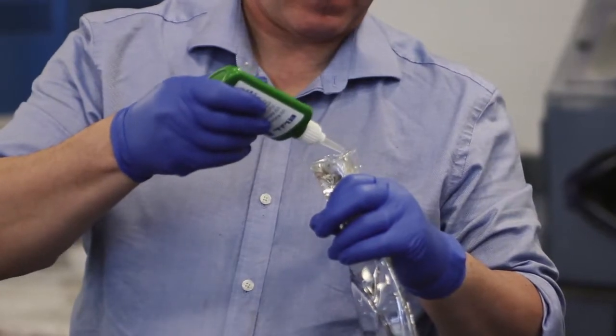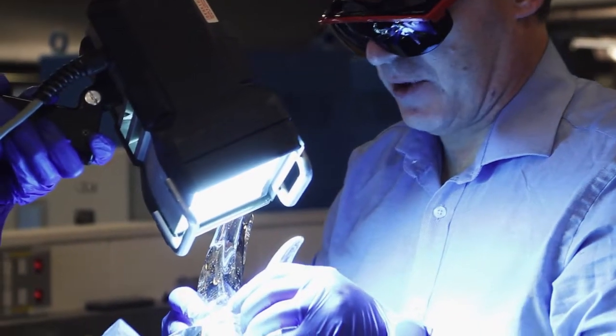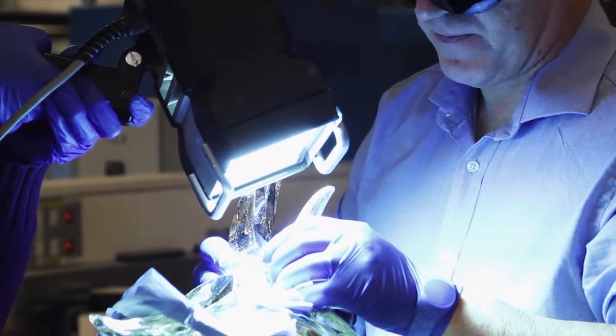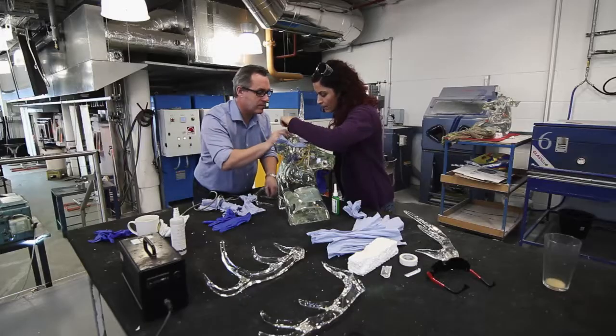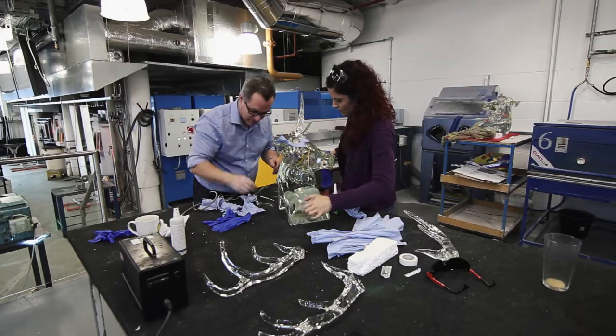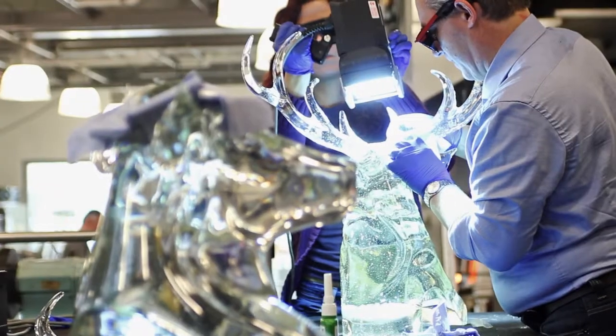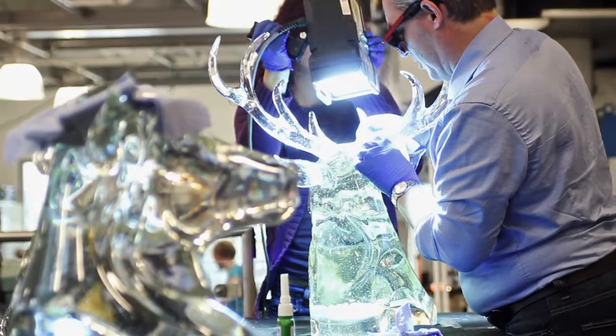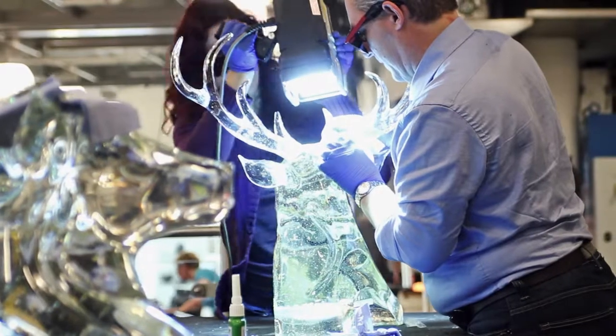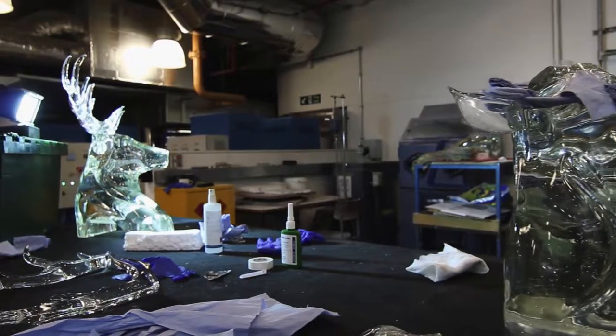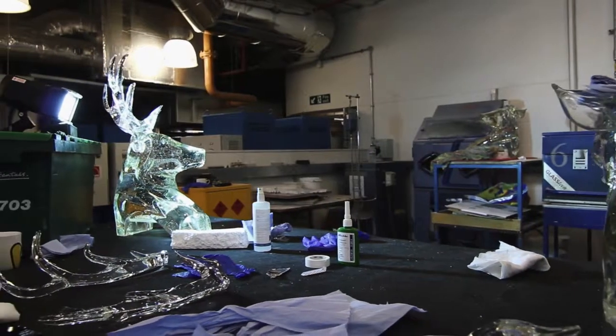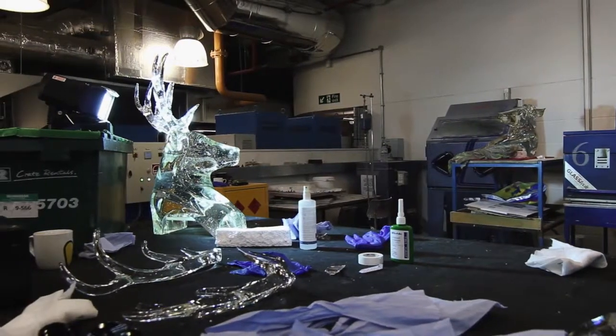So this is essentially the last stage of the whole process. We just make sure that the place of contact between the antlers and the stag is completely leveled, completely flat. We clean it all up nice and tidy, and we use a thick UV glue to glue the antlers.